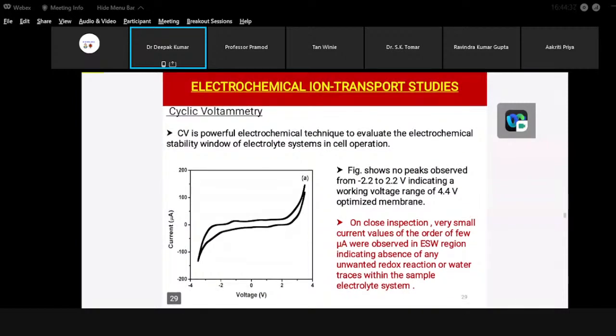For investigating the electrochemical stability window of the electrolyte, we have performed cyclic voltammetry, and for the chosen electrolyte system we are able to get a working voltage range of almost 4.4 volt, which is good enough for an electrolyte system. For this voltage region, we have also observed that no unwanted redox reactions are seen, which is also a good part of the electrolyte system.